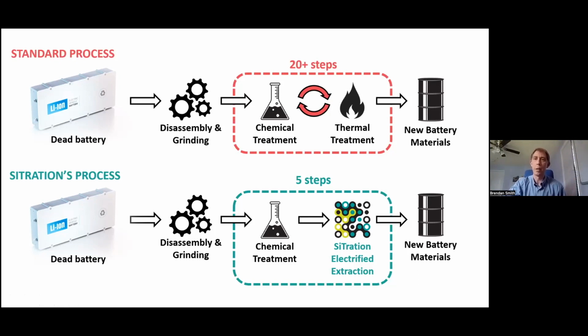And so what we're doing is actually shifting the paradigm here to something that looks very different, much more streamlined, and much more efficient. So we're actually plugging into the existing process where we take this material that's been either ground up or burned down to a slag. It still gets dissolved in the acid the same way as currently being done. But in our case, from here, the difference is quite stark. So instead of using an entirely chemical and thermal-based treatment method, our process is totally electrified in nature. And what we're doing is we're drastically reducing the number of stages by pulling out the lithium, cobalt, and nickel compounds in the first three or four stages of the process. So we don't have to go through 20 stages, pull out all the contamination. We pull out the valuable stuff as an initial step. So you can see here the high-level impact, what that means in terms of process complexity.